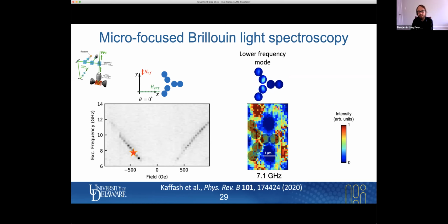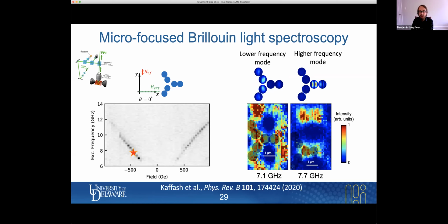Now we can also take a look at the high frequency mode. And indeed, we see that the dynamics are mostly located in the horizontal elements. So the bottom line here is we can use this type of artificial spin ice for the observation of localized dynamics in those systems. So that's the first step. If you think back about the idea of using these strings to send information along these strings encoded in spin waves, this is a first step showing that there are indeed localized dynamics in these lattices.